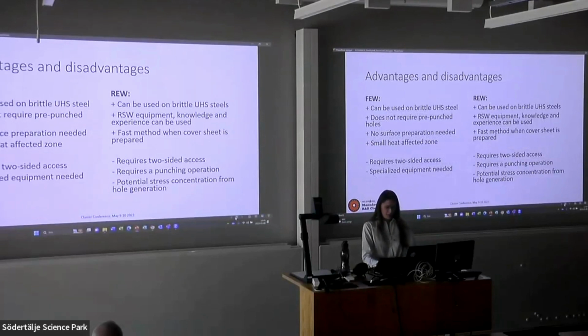So some advantages and disadvantages. Of course, both these methods can be applied to brittle ultra-high strength steel. That's the reason we have them in the project. If we look at friction element welding, this does not require a pre-punched hole, no surface preparation, and you get a relatively small heat affected zone. It does require 2-sided access, and you also need specialized equipment.